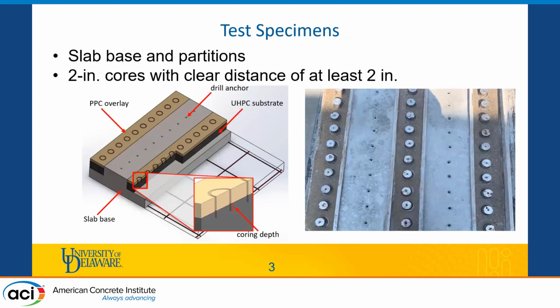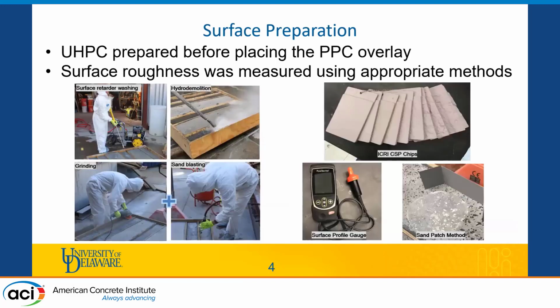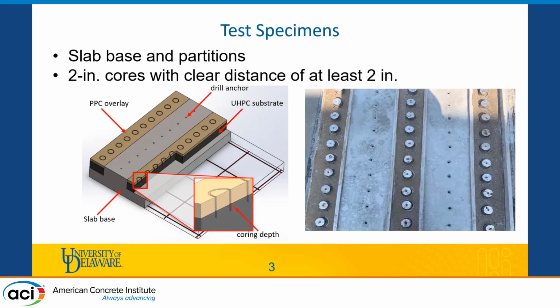Bearing this in mind, we prepared our test specimen to have a slab base, just to have some level of robustness in our specimen. We have nominal reinforcement in there to control thermal shrinkage. On top of that, we have our ultra performance concrete, which is 3 inches deep. On top of that, we applied our PPC material, which was 1 inch deep. We partitioned the slab to allow us to have areas where we can put our drill bits such that we can drill on either side of the slab. Each core has a diameter of 2 inches, and this is as recommended by ASTM C1583.